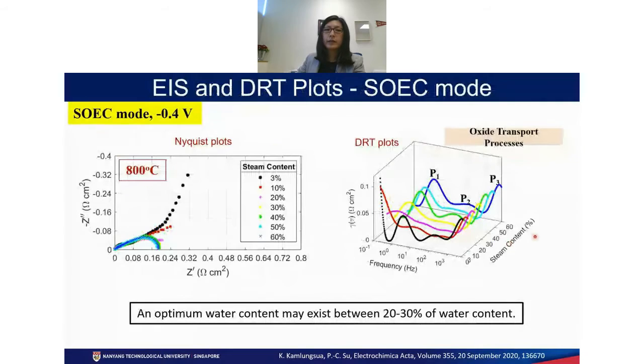Okay, now let's look at the most concerned result, the SOEC result. We can see that when the moisture content is 3%, this black one, it's still very low, it's expected that the impedance is very high because there is not enough water for the electrolysis. And as the moisture content increased to 10%, 20%, the impedance dropped very significantly. And finally, when the water content is much higher, it doesn't really change too much.